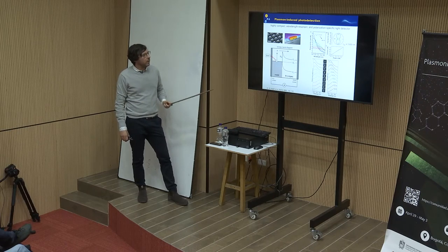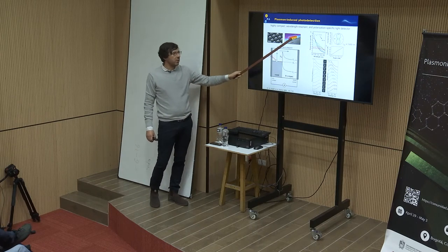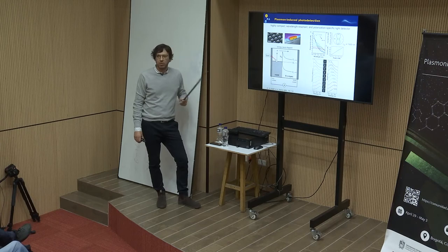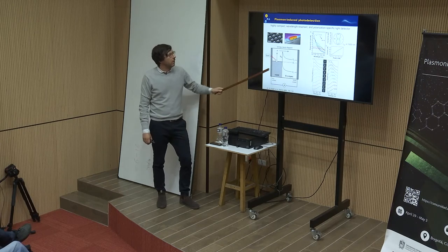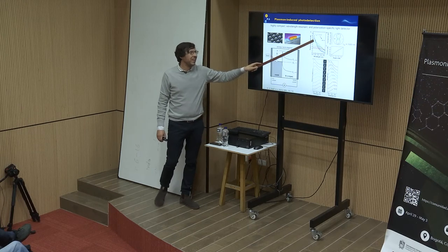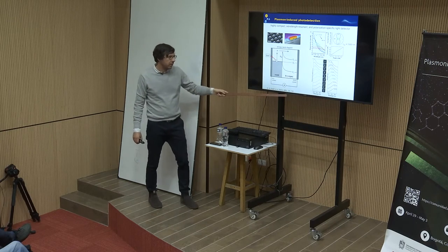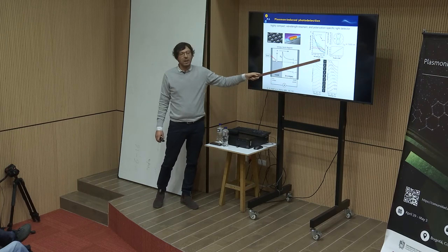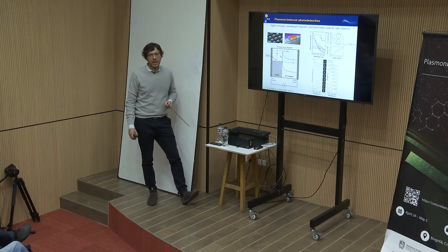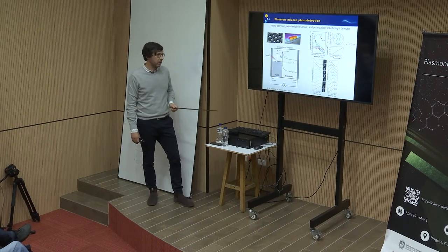And as we can see, what they did was to prepare different resonators with different sizes, as we can see here, and measure the photocurrent generated by the illumination at different wavelengths. You can see here the responsivity of different devices having different sizes of nanostructures. And as we can see here, the photocurrent spectra that they registered was following the localized surface plasmon resonance of this nanostructure, demonstrating that this current was coming from the hot electrons coming from the deactivation of the plasmon itself.